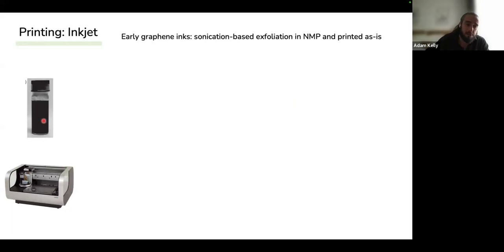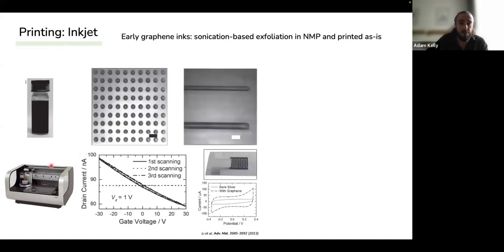So this would have been just a vial, graphite and NMP, and put in a sonic bath for a range of time and then centrifuged once to remove large unexfoliated material and then printed using a Dimatix printer. And what they found was this worked very, very well. This was done by Max Lemme's group in 2013.